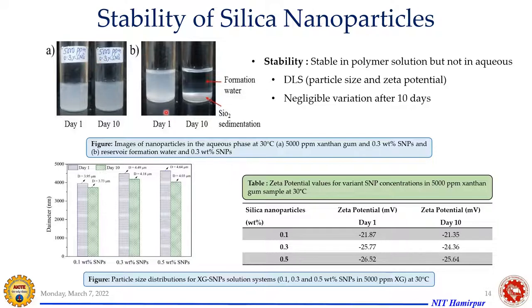and nanoparticles. Previously, researchers have used nanoparticles with water flooding, and the results were not encouraging, because in their experiment they had not identified the stability of the nanoparticles. If the nanoparticle is not stable in the suspension, then the properties we're looking for will not be effective, and you cannot have higher oil recovery. So the first thing that we studied in our experiment was we were trying to check the stability.